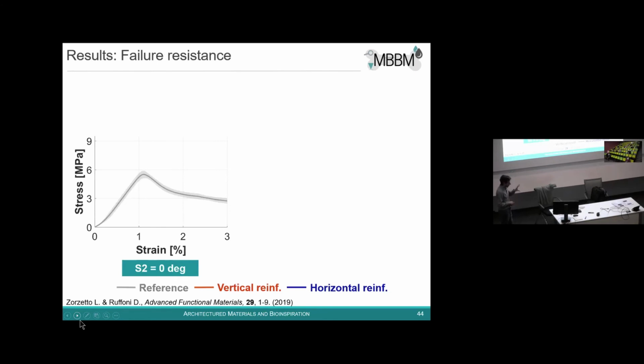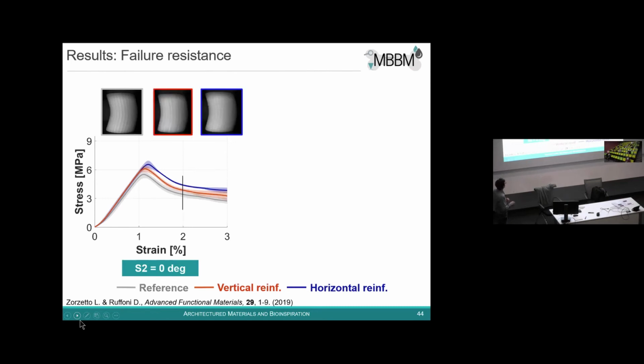Then we performed experimental tests to failure. And what we see is the following. This is the behavior for the situation of straight fibers. So we have a cylinder with straight vertical fibers. This is not a big surprise. When we compress this system it is buckling. So it's going into buckling failure. And if we add either vertical reinforcement or horizontal reinforcement, well, we don't change the behavior too much. We have a small increase in the buckling strength, but the behavior is substantially the same. And so we are not influencing and reinforcing the structure much.